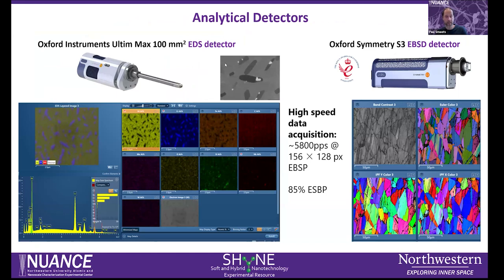We also have analytical detectors present. We have an Oxford Instruments EDS detector, relatively large area. This is just an example of a cross-section of that metallic alloy where we have the higher Z contrast regions, about a 50 nanometer region that we can see here.